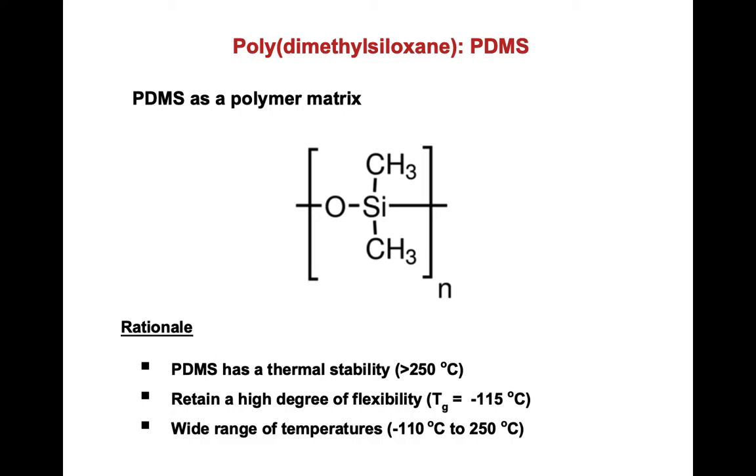Previously, the dielectric constant of the three kinds of material was a function of temperature and frequency. So, in order to achieve temperature and frequency independent dielectric constant, researchers introduced polydimethylsiloxane (PDMS), a flexible polymer matrix, to prepare ceramic polymer composite material.